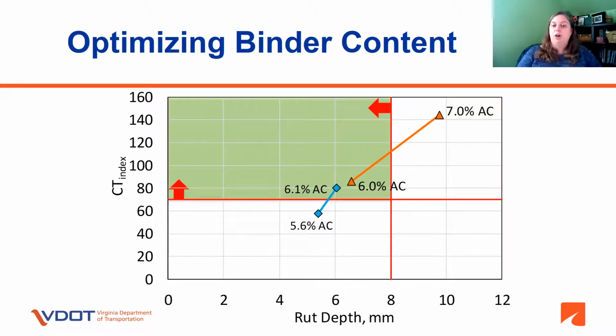You can see the result of over asphalting in the orange mix. If you have a mix that should be optimized at approximately 6% asphalt, and you have an actual over asphalted to a 7% AC, you're going to be exceeding the rutting while showing very good cracking. But you have to meet both specifications.